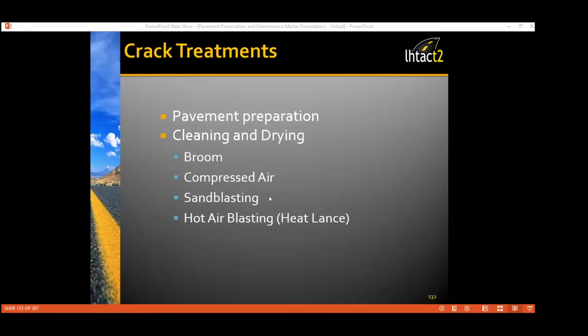And so the next step then, we want to clean and dry the crack, and for the best results, cleaning with compressed air or sandblasting is a good idea. Hot air blasting uses a heat lance to dry the crack and will work very well, because moisture is going to inhibit the bonding of the crack sealer to the wall of the crack. So the biggest thing I think for preparing the crack is to make sure that it's clean and dry before you put the material in.